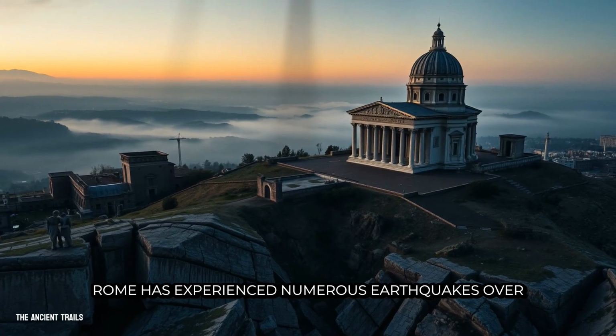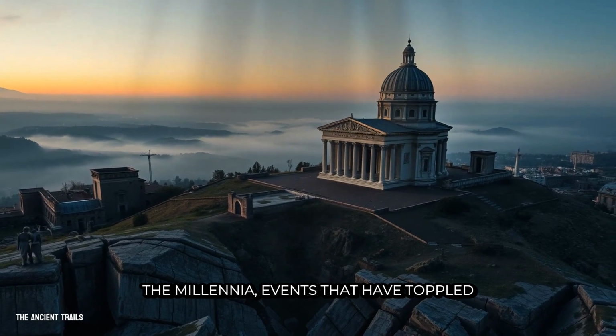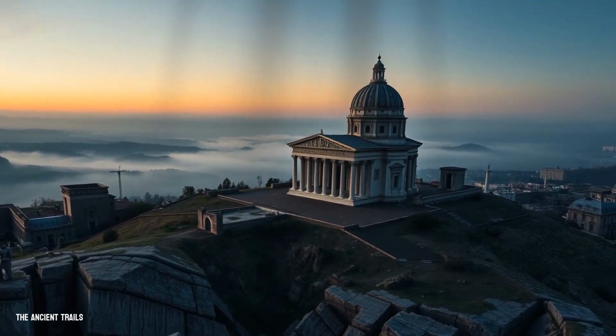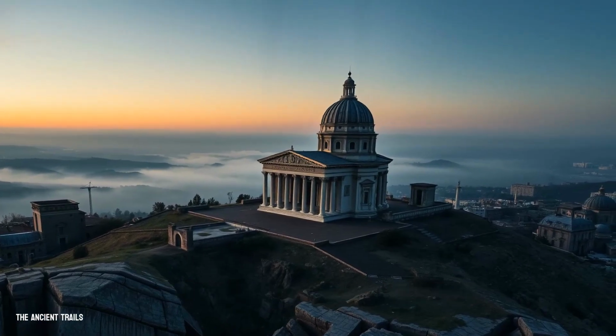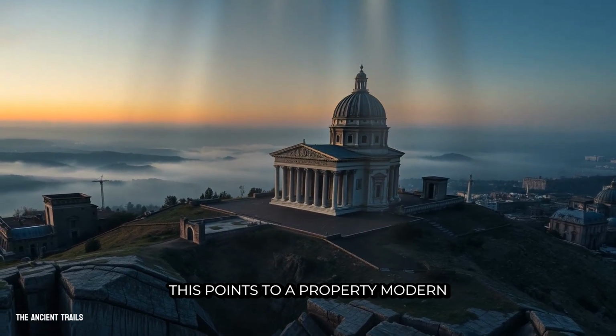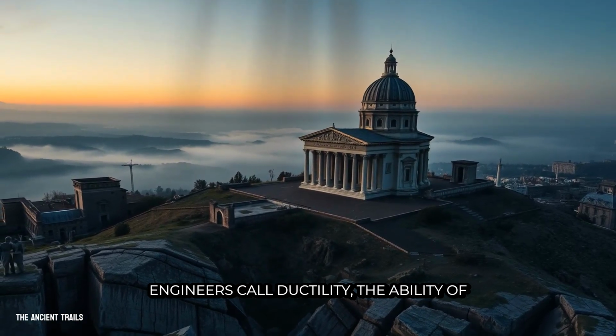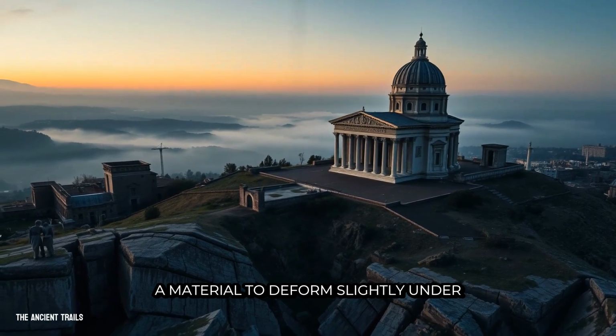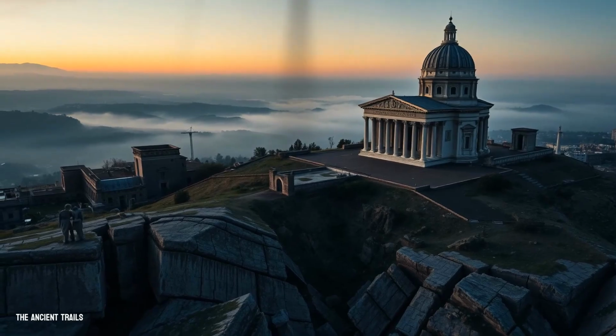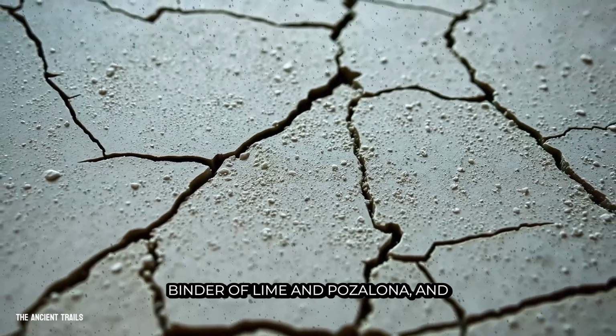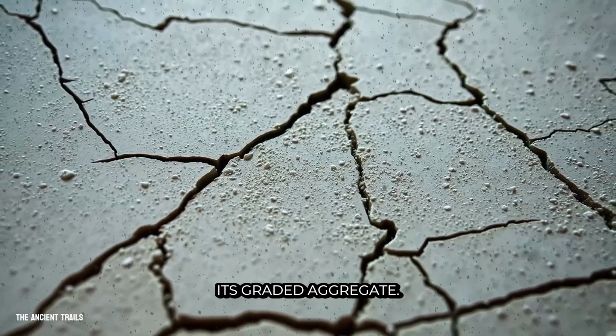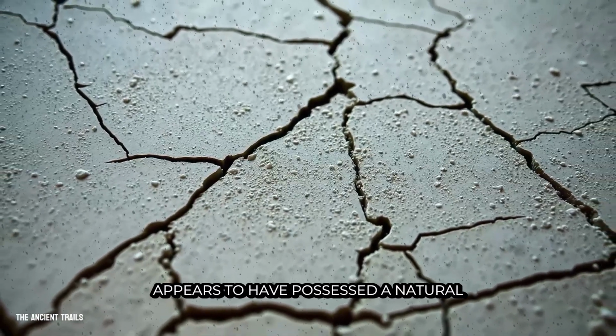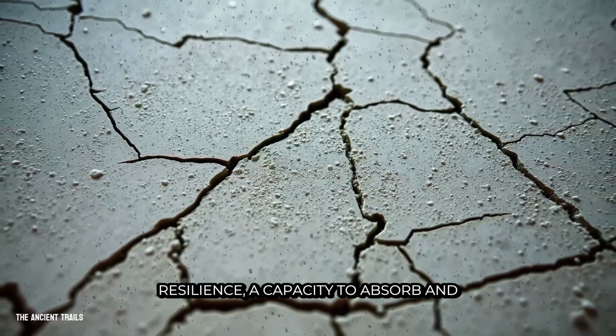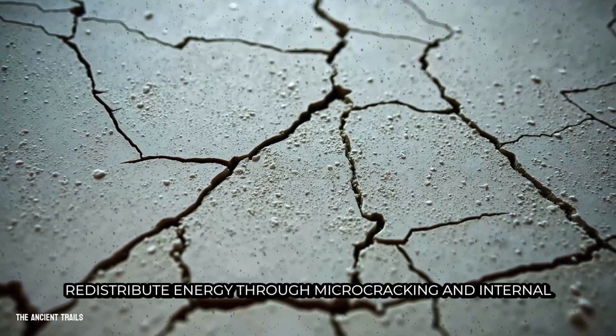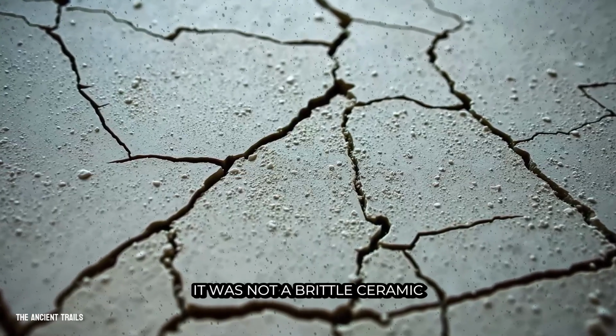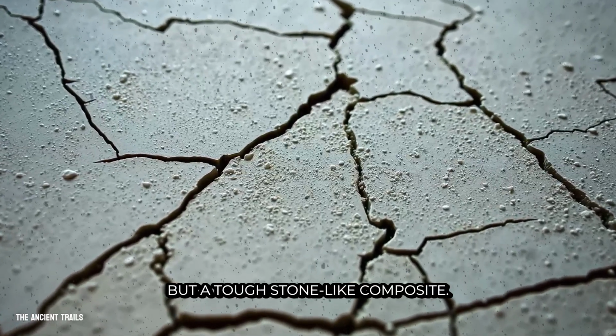Rome has experienced numerous earthquakes over the millennia, events that have toppled countless later structures. The Pantheon's dome has swayed and settled, but it has never shattered. This points to a property modern engineers call ductility, the ability of a material to deform slightly under stress without fracturing. The Roman concrete, with its complex binder of lime and pozzolana and its graded aggregate, appears to have possessed a natural resilience, a capacity to absorb and redistribute energy through micro-cracking and internal adjustments. It was not a brittle ceramic but a tough, stone-like composite.